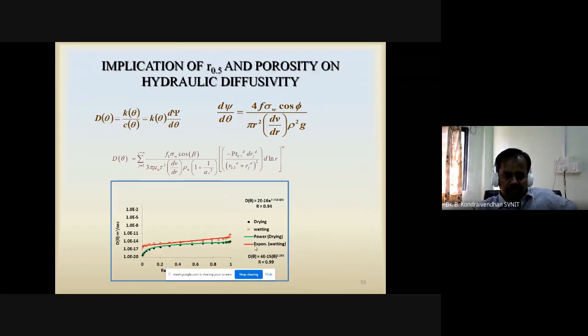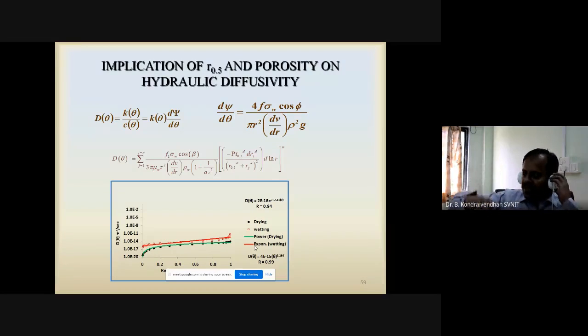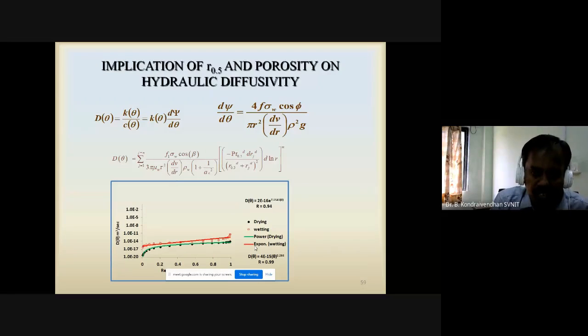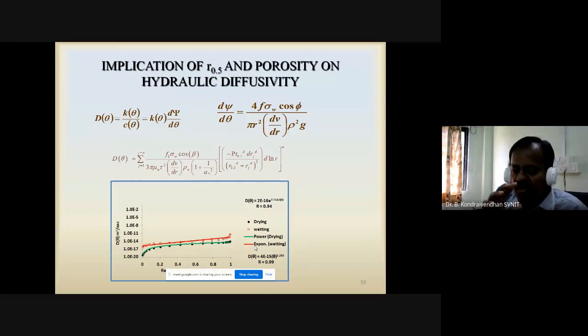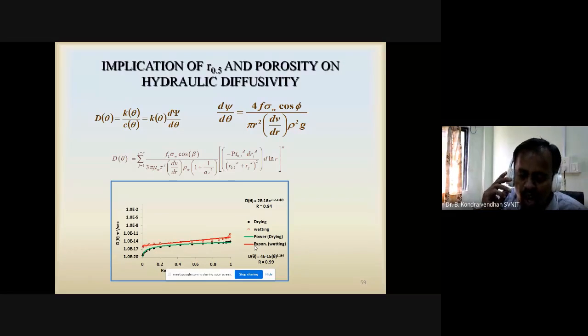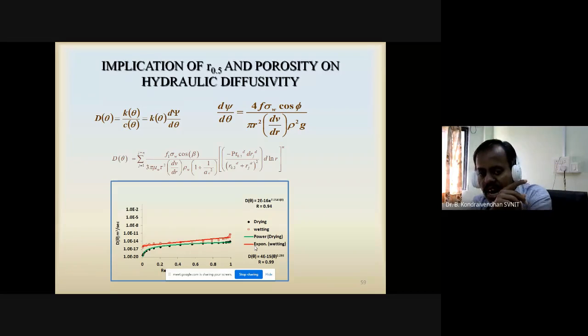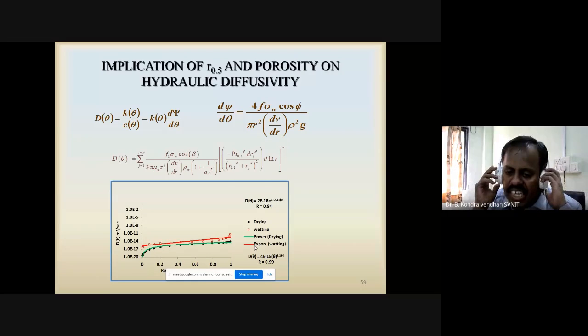Next we have gone for the hydraulic diffusivity. Hydraulic diffusivity is nothing but hydraulic conductivity divided by the specific water capacity. So we can also modify K(theta) into D = K(theta) / (d psi / d theta), where psi is called suction head. These formulas are already available in literature; we only modified the K(theta). By using this, we have calculated the hydraulic diffusivity for both the wetting and drying cases.